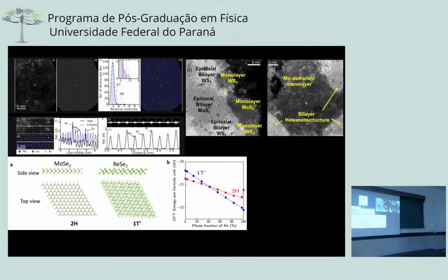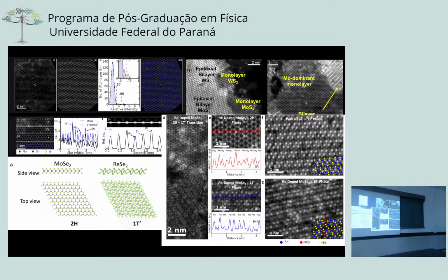So we started playing around with doping, changing concentration, started making alloys and heterostructures. So what you see here is tin-doped moly, tungsten, 2D material alloy. We started having phase transformation. So MoSe2, which is 2H, we can dope with rhenium and have a different crystal structure, as seen in atomic resolution. This region is 2H, here is 1T prime.